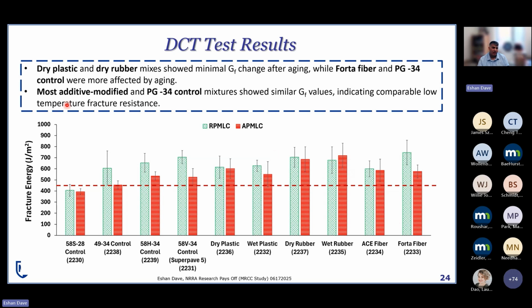So what we saw is the dry plastic, dry rubber showing relatively less drop after the aging. The wet rubber obviously showing very good properties and even seeing a slight increase after aging versus some of the modified ones. Obviously, control was already below the threshold, but even the 58H-34 as well as Superpave 5 both showed an appreciable decline in their fracture energies after they had gone through aging.